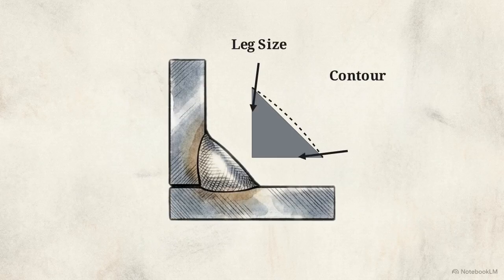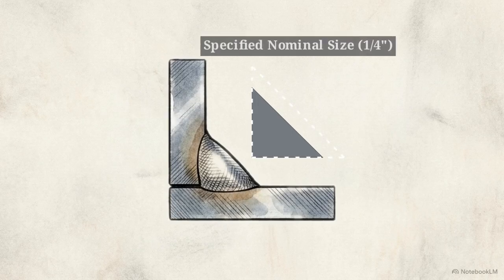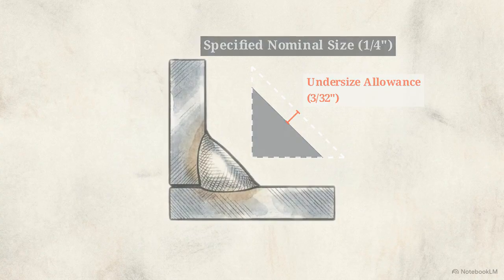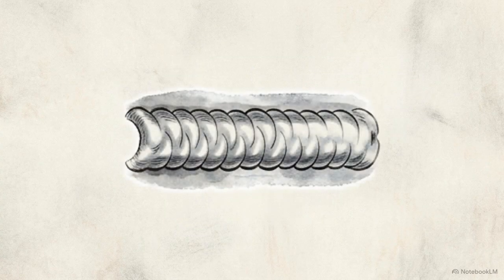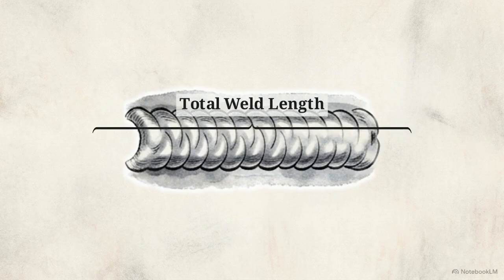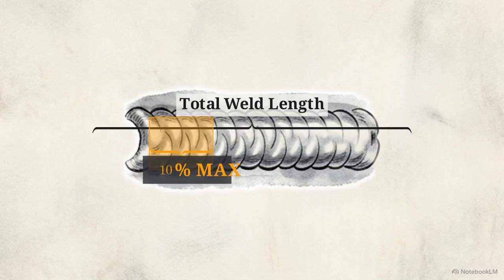The AWS D1.1 code does provide an undersize allowance. A weld can be slightly smaller than specified. For example, a weld with a 1/4 inch nominal size can be undersized by up to 3/32 of an inch. This diagram illustrates how that rule is applied in practice. While slight underruns are permitted, those undersized portions are strictly capped and cannot exceed 10% of the total weld length.